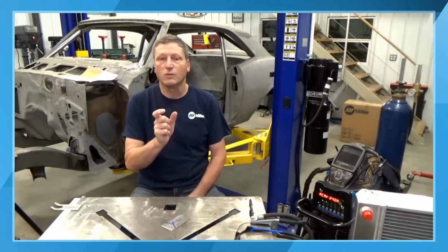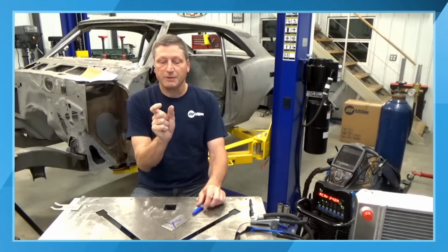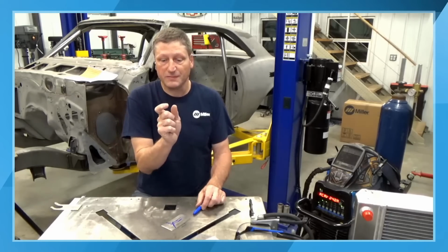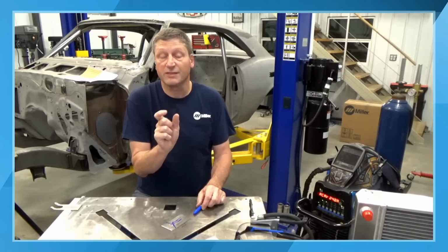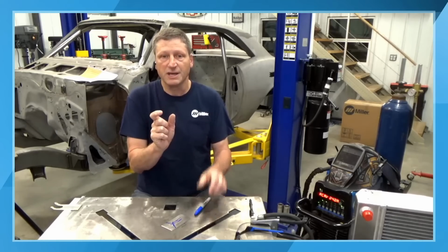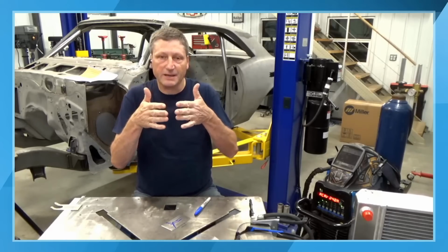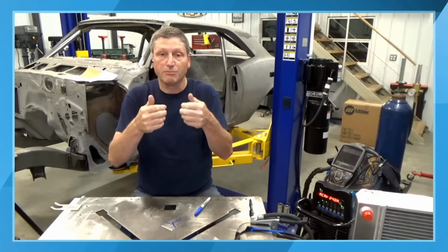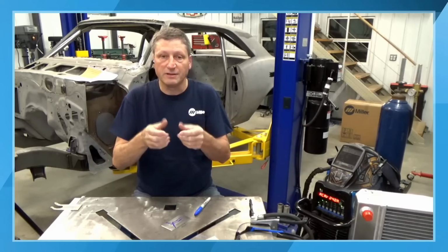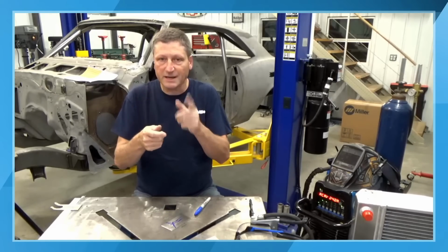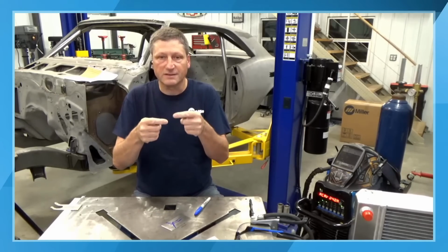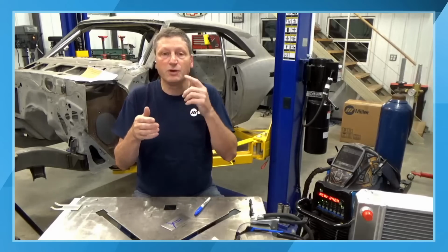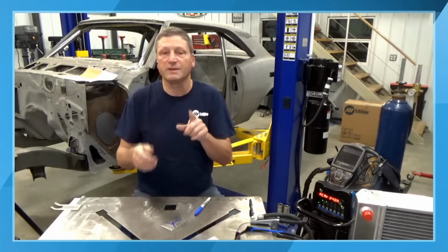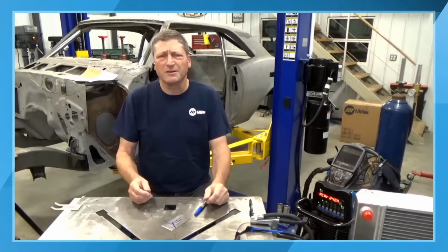If you're doing lots of welding, so I might be welding in a piece of half inch thick or even thicker aluminum, making a patch. And I've got that patch and the block beveled, so the point where it's not an open root, but it still sits in there fairly tight, but I'm putting a lot of weld bead. Those are going to be the areas where I'm going to be peening.